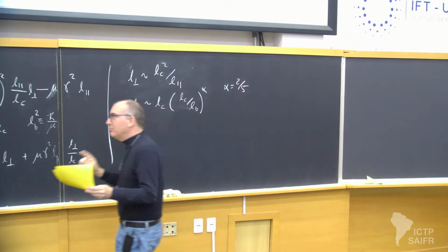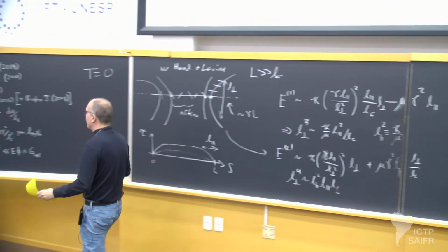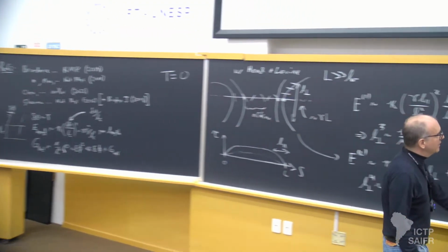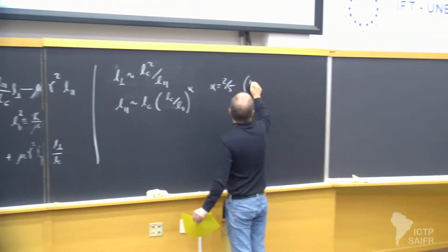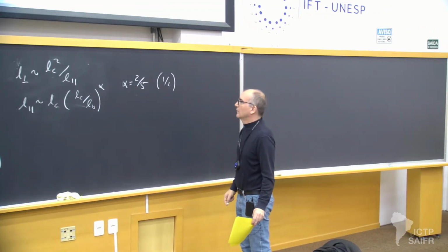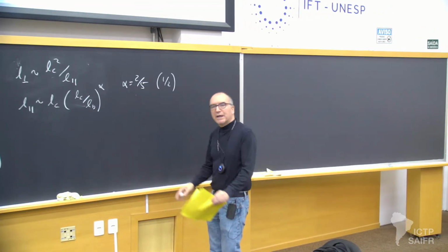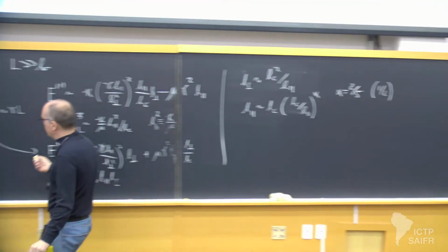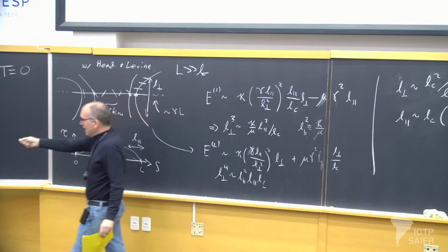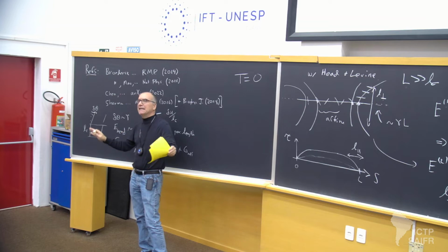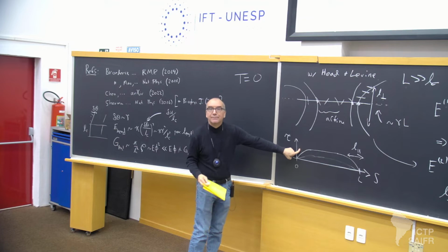A much better calculation of this actually shows that this exponent should be 1/2. Okay, but you get the idea. I wanted to go through this argument because it shows that this non-affine limit of the shear modulus for a network is mechanically inconsistent with the high molecular weight limit. Something else has to happen, and it's this.